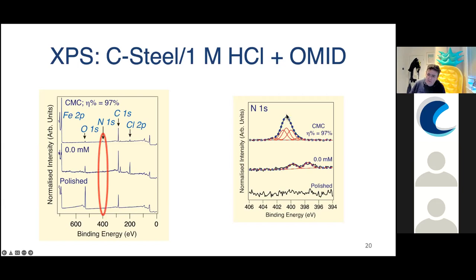But then we get a bigger peak once it's well inhibited, which suggests the molecule is clearly adsorbing onto the surface. And we fitted this overall peak with five individual components, five individual peaks. Now, you might be a bit surprised at that, because remember, I just told you before, there's three different nitrogens in this molecule. So why do we have five peaks? Well, hopefully now I'm going to be able to convince you that we have a reasonable case for why we fitted with five peaks. And this was not a simple process. It took rather a long time.